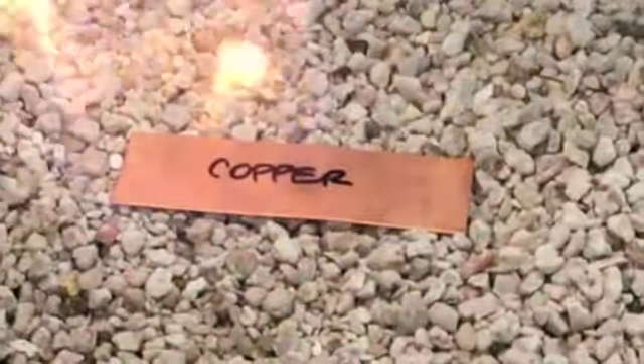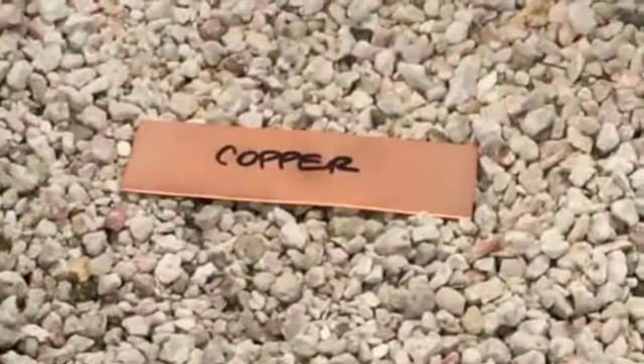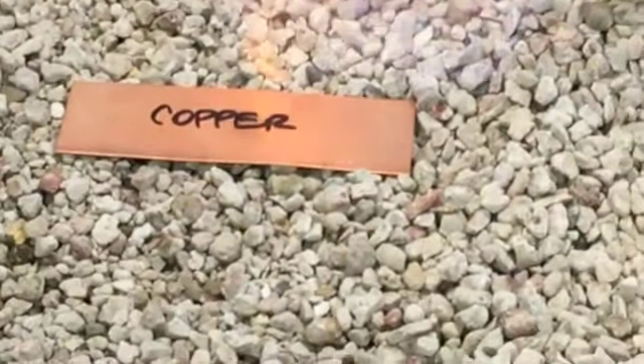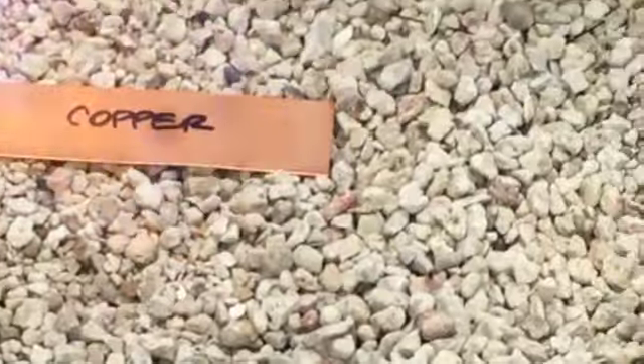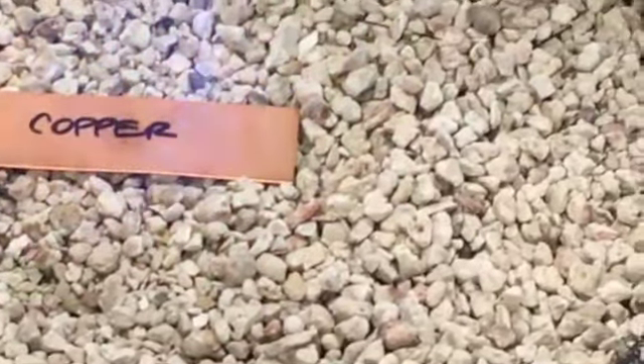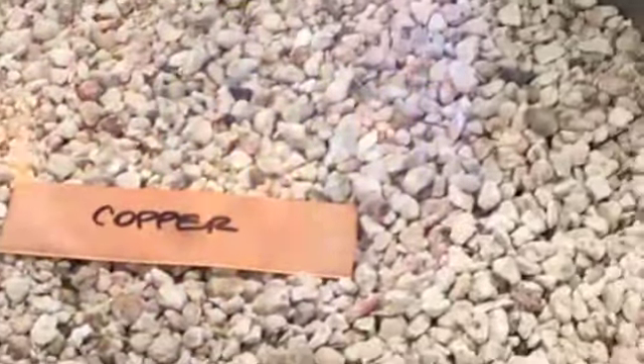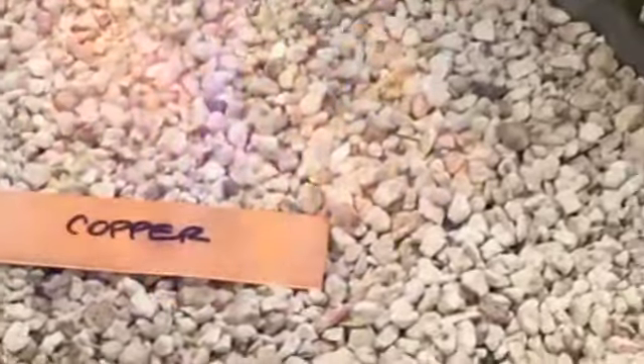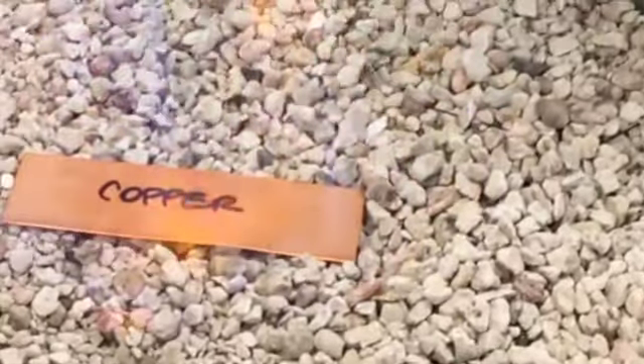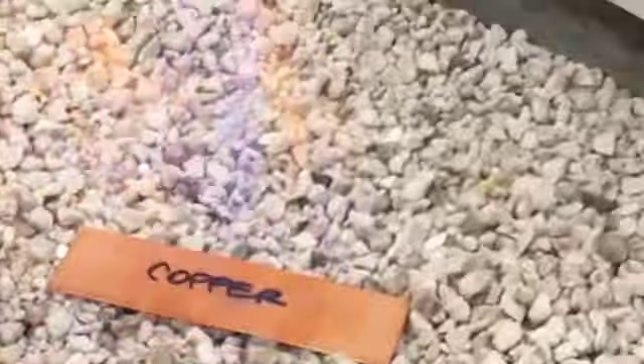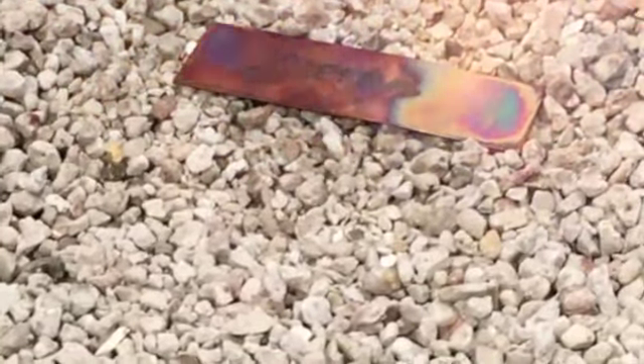Move the flame around your piece as you heat it to keep the heat even, and watch for the visual cues that tell you when your metal is at its annealing point. Copper will oxidize almost as soon as you start heating it. As you continue, the oxides will shift and change as you move the torch, and the air is able to get to the surface. Darker and darker, and then it starts changing colors more dynamically.